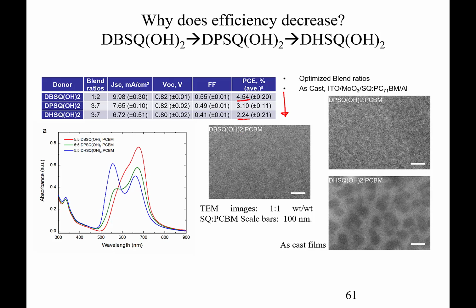to 2.24%. And these are films that are unannealed, and what we have claimed is that the reason for this drop in efficiency is because when we take the as-cast hexyl side group Squaraine, these materials don't mix well at all with the PCBM. So all as-cast films with the DH, with the hexyl side group, already give us these large domains, this phase separation in here. We can start to see with the pentyl groups some very small domains form a little bit. This is transmission electron microscopy, but really with the mixture of 50-50 by weight of dibutyl Squaraines in here, the TEM basically shows that these are very well mixed, very small domains. And so actually we're seeing that those small domains give us a high efficiency device.